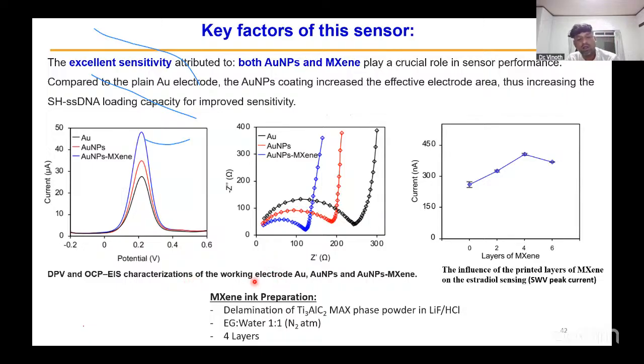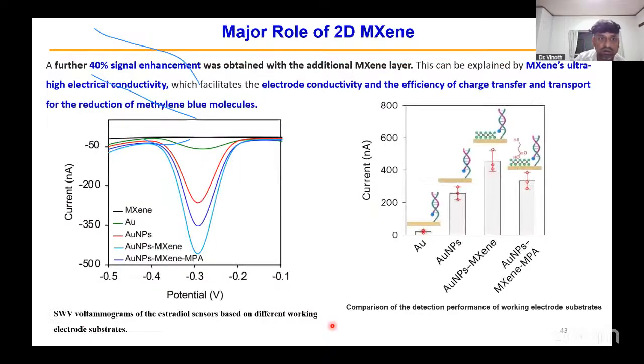Here in this study we prepared the MXene by delamination of MAX phase titanium aluminum carbide with lithium fluoride and HCl. We used ethylene glycol and water in a 1:1 ratio, and we developed 4 layers to prepare our sensor working electrode. Here the MXene shows a 40% signal enhancement with the additional MXene layer, which is due to the high electrical conductivity, which facilitates the electrode conductivity and the efficiency of charge transport for the reduction of methylene blue molecules.